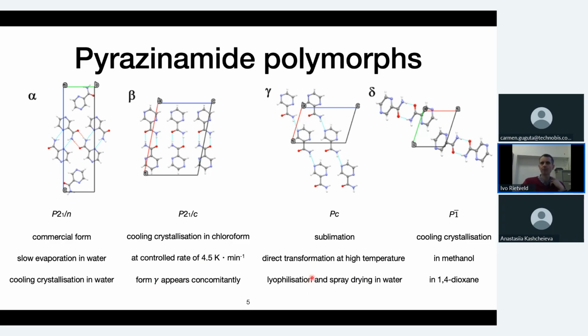And then the delta form, kind of, say, a brother or sister of the alpha form, because delta is also stable relatively close to room temperature, and you can therefore get it by cooling crystallization, either in methanol or 1,4-dioxane and some other solvents too, but relatively easy to obtain.